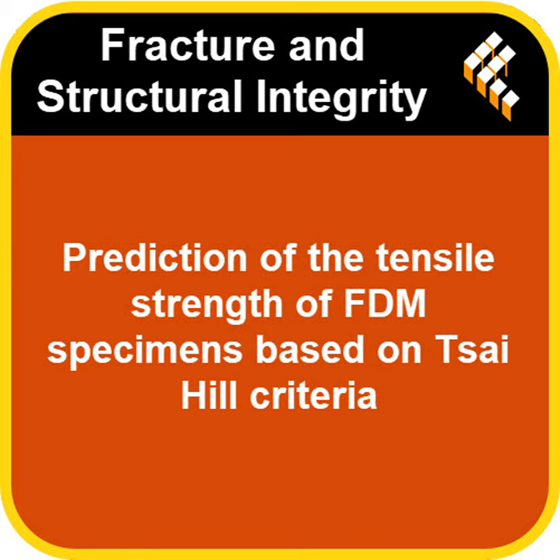And the study really focused on two main things about how they laid those lines, didn't they? Exactly. The direction inside the part, the raster orientation, and whether it had that extra outer skin, the contour. Precisely. Raster orientation is all about which way those melted plastic filaments are pointing within each layer. Okay. Like you said, the grain. Imagine the planks in a wooden floor. That's sort of the idea. This study tested three main directions relative to where they were going to apply the force later on. Right. What were they? Straight along the direction of force, that's 0 degrees, then crisscrossed at angles, plus and minus 45 degrees, and finally perpendicular to the force, so 90 degrees.